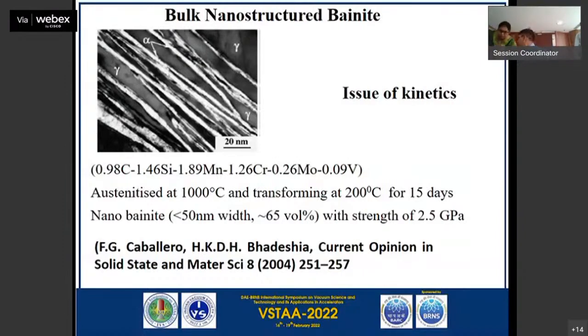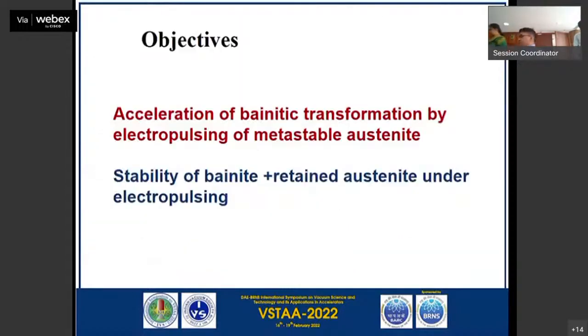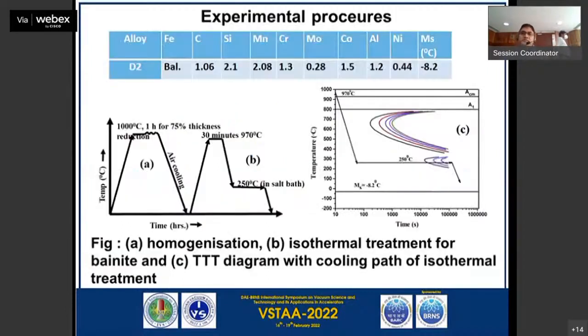So the objective: we have taken the objective to accelerate this bainitic transformation kinetics and to see the stability of this bainite as well as retained austenite under electropulsing condition. Next slide, please. We have made the material by vacuum induction melting, homogenized, and then austenitized the material.